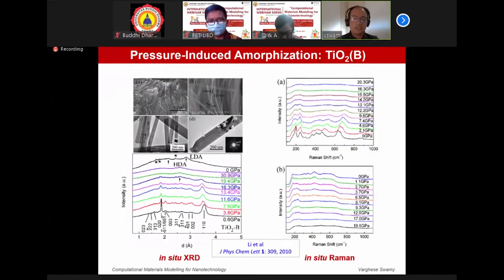This is not my work. This is work from the literature. They have also found titanium dioxide phase B. It is another metastable structure, very similar to anatase. When you take nanoparticles of 15 or 20 nanometers and compress them, as you increase the pressure, you can see that the material becomes amorphous. You can see the diffraction peaks disappearing at around 12 or 13 GPa, and then it becomes disordered. So two materials act very similarly.